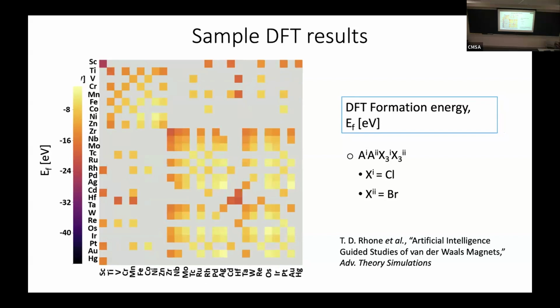We also care about chemical stability. This just means you want to be able to make the material in the lab, so it should be stable once you try to make it in the lab. And a rough proxy for chemical stability is a thing called formation energy. And if it's above 0, you know for sure that you can't make it in the lab. If it's less than 0, you know you have a chance. It's not a guarantee, but you have a chance.